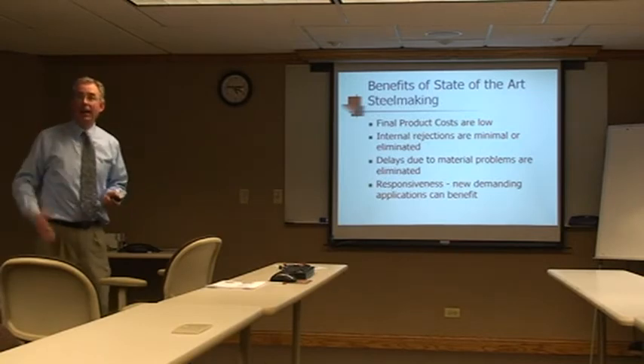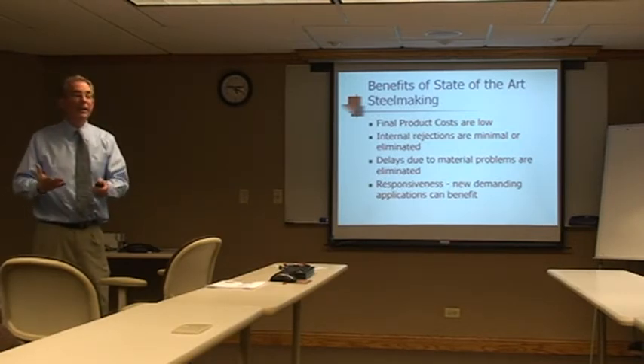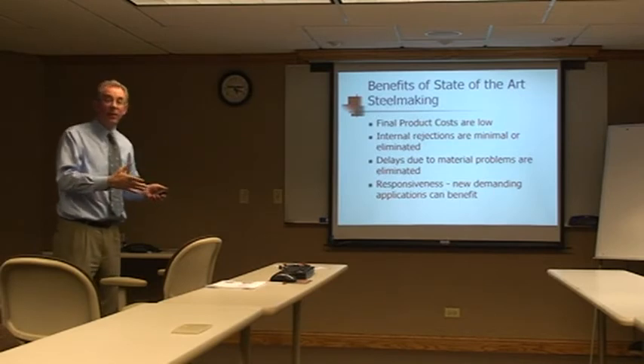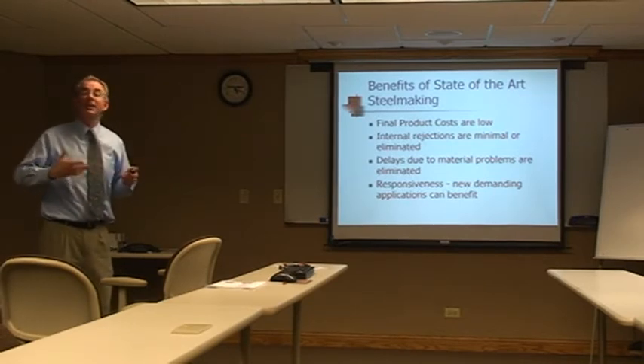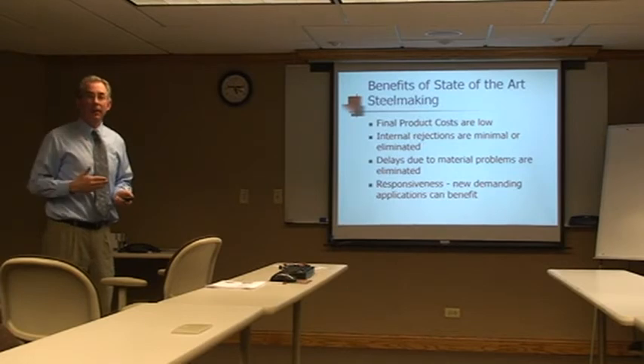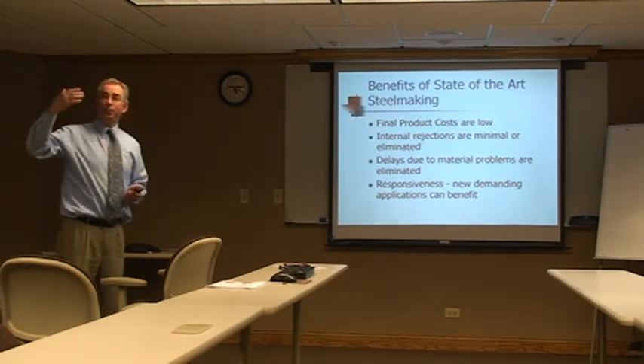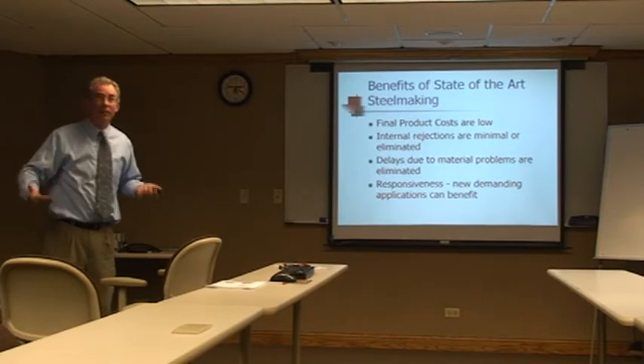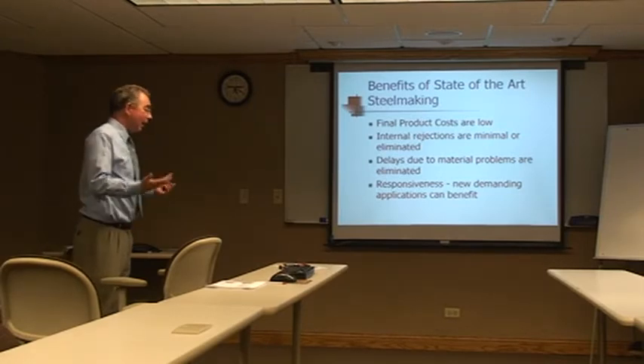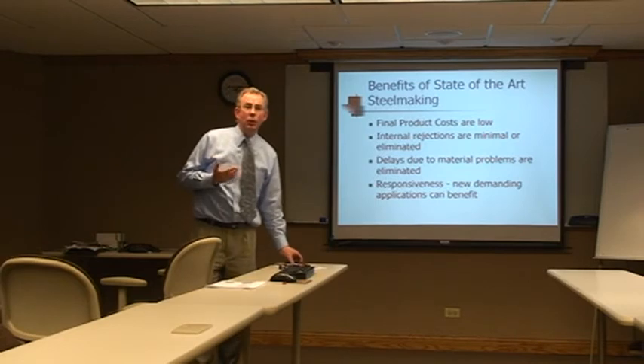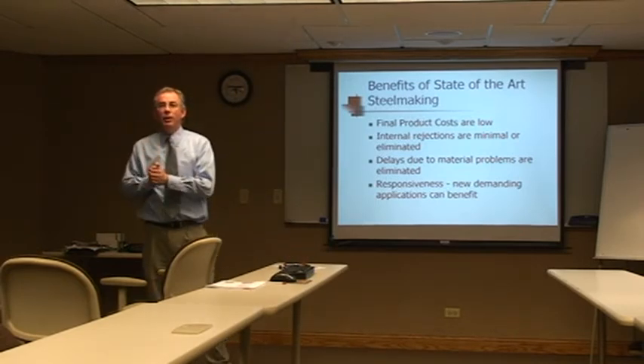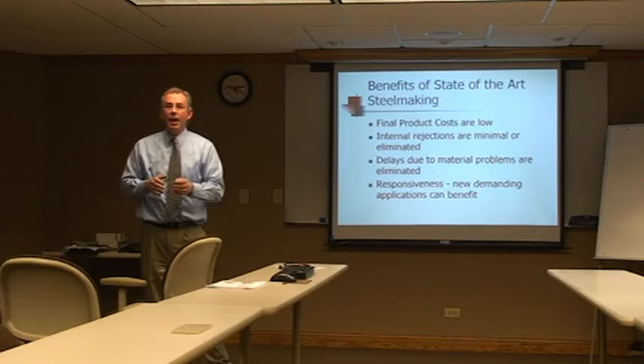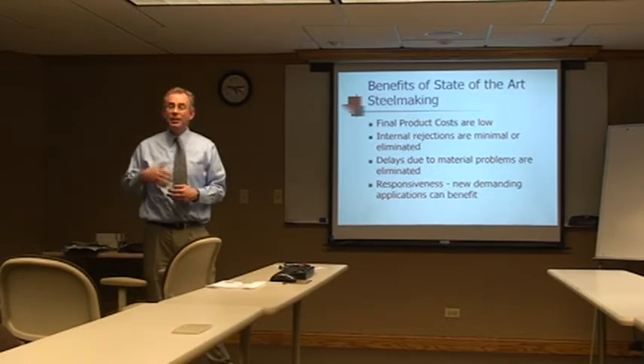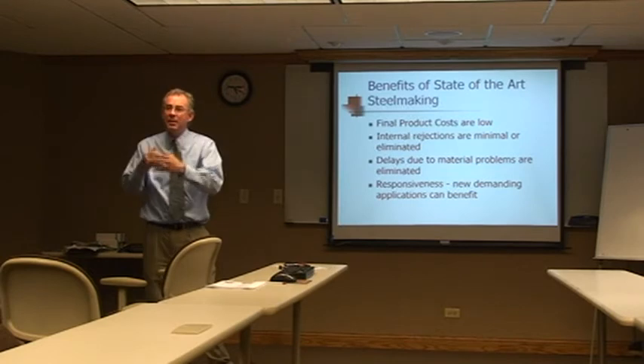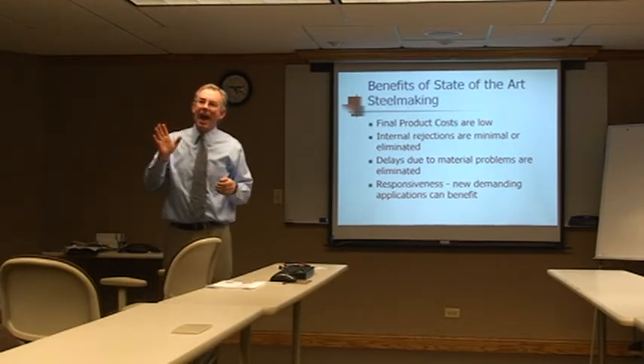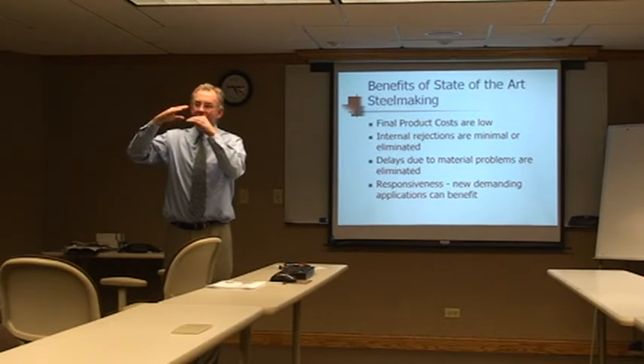And by doing that, any kind of rejections or anything that you would need to deal with, or that we would need to deal with internally because of inconsistent production, causing delays delivering material to Scott, or delays processing here at Scott because of problems, are reduced. And responsiveness. The things we can do with our steelmaking equipment and chemistry control, we can make very tight chemistries, and process-wise, it's extremely repeatable. We talk about teeming temperature as an example. It's a 0.5% variation in our teeming temperature window.